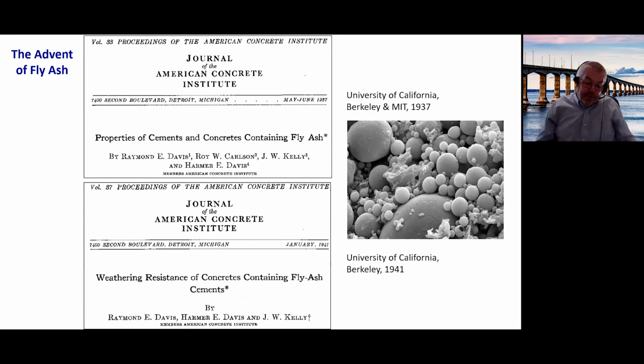So what happened next? Well, around about 1940 it was discovered by work at the University of California in Berkeley that fly ash, the residue from burning coal in a coal burning generating station, was indeed a pozzolan, and did many of the things, in fact, all of the things that natural pozzolans did. It could reduce the heat, it could control ASR, control sulfate attack, and it was indeed a viable alternative to natural pozzolans. And of course, any natural pozzolan requires some degree of processing, even if it's just digging it out of the ground, drying it, grinding it, whereas fly ash could be taken almost directly from the precipitators and used in concrete with very little processing.